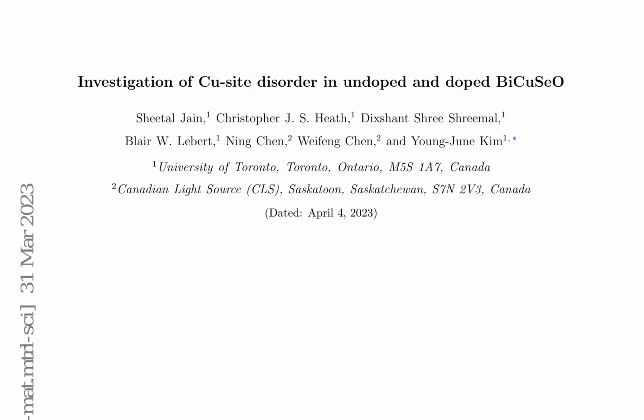The absence of an increase in lattice constants upon Ag doping at room temperature suggests a large void around the Cu site in BiCuSeO. This temperature independence and large void support the rattling mode scenario, localized on the Cu site, which may contribute to the intrinsic low lattice thermal conductivity of BiCuSeO. Furthermore, the mass defect introduced by Ag doping, coupled with retained rattling behavior, can explain the further lowering of lattice thermal conductivity in BiCuSeO. The combination of XRD and EXAFS has proven to be a powerful technique for comprehensively understanding the structure and dynamics of undoped and doped BiCuSeO.